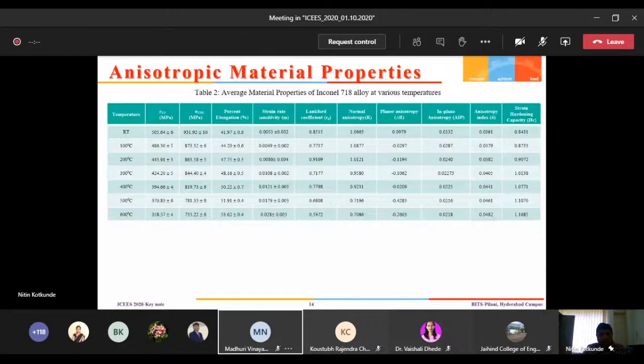Here we have represented only R0, and based on that we calculate the normal anisotropy and planar anisotropy. If normal anisotropy is good, it means the material has good formability, but unfortunately, if you see here, all the values are around 1 or less than 1, which means it has poor formability, and it is more challenging to form. Planar anisotropy indicates the earing tendency in a material, which is low, so it has a low earing tendency. We should not worry much about the earing tendency.